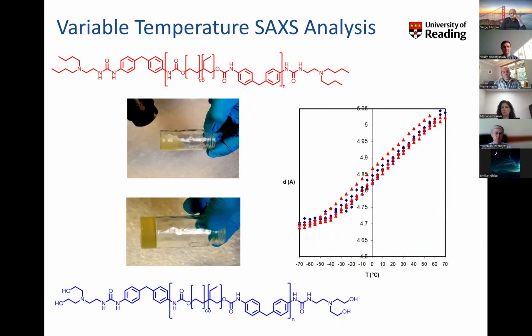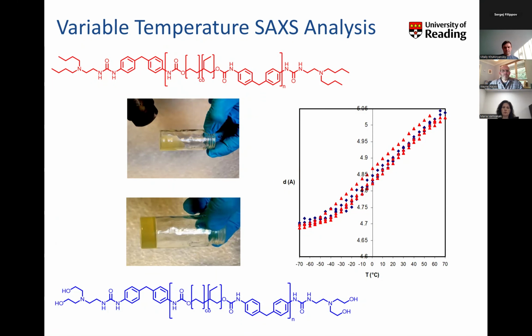Now, what was also useful in terms of the hot melt adhesives was to look at their thermal properties. And so we did variable temperature SAXS analysis across a 140-degree temperature range. And what we could see was that we could thermally cycle these materials reliably. There was no degradation across the temperature range that we studied. And this led us to another area, a field where we're trying to extend the lifetime of polymers, and it directly addresses one of the main points that came out of the previous talk in terms of how humans use polymers and how we should be mindful of how they degrade.